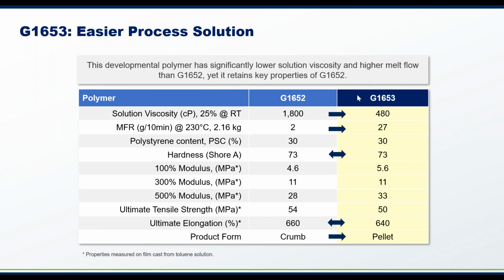elongation. So in this table, you can clearly see that G1652 compared to G1653, G1653 has a much lower solution viscosity, and hence it will also have a much higher melt flow for the hot melt-based systems. And yet a lot of other properties are very similar. For example, hardness, ultimate elongation, the majority of the tensile properties. And again, another primary difference is the crumb. G1652 usually comes in a crumb form where it generally needs to be deblocked prior to use, whereas G1653 comes in a pellet form.